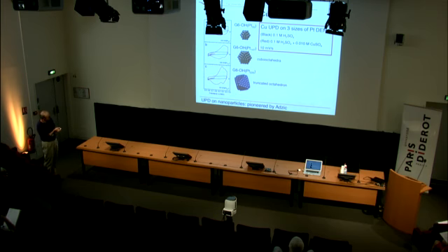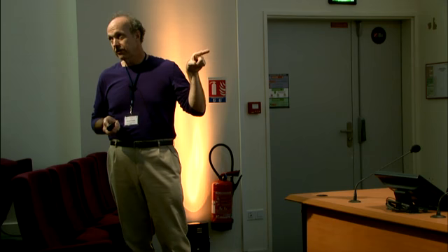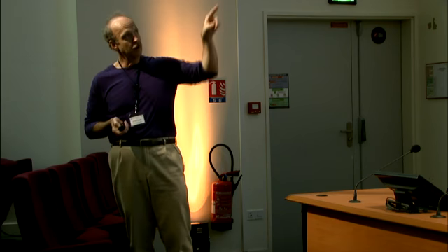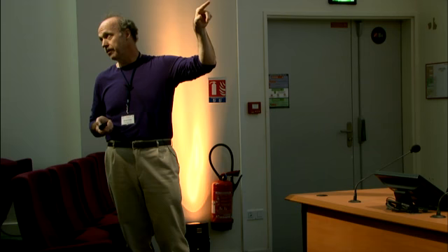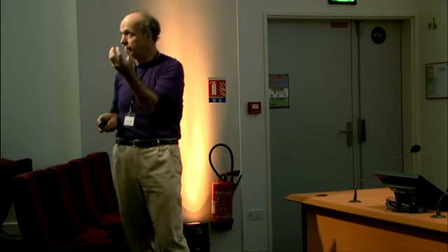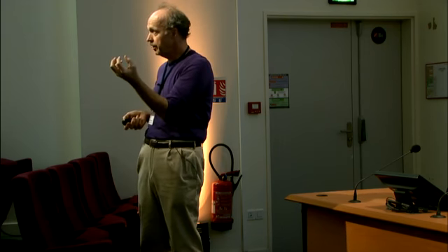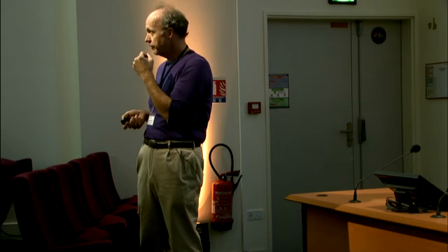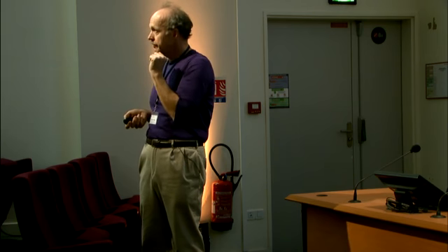Now we go to a little bit bigger one, a little bit bigger dendrimer-encapsulated nanoparticle. So this has 3 closed shells. You can see now here's the deposition, stripping. You can see there's a little more charge, which you would intuit there should be. When we immobilize the dendrimers on the electrode, even though the particles have different sizes, the same number of dendrimers are immobilized, because the dendrimer is what's taking up the space on the electrode. So there's always the same number of those. So the number of particles is the same, just their size is changing, roughly.